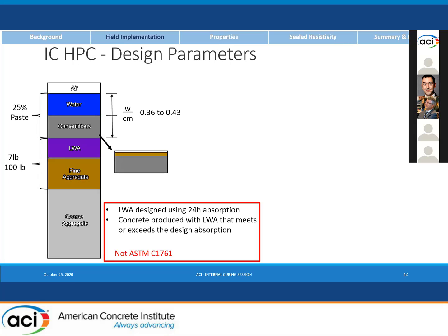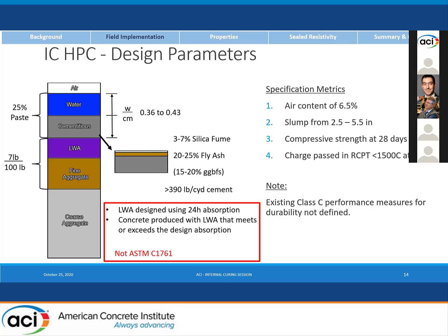For the cementitious materials, we were looking at a ternary system, so there was silica fume, fly ash, or slag, and a minimum cement content. The specified metrics that we're looking at was target air, target slump, fairly trivial compressive strength for this class of materials, and then an RCP value of less than 1,500 coulombs.